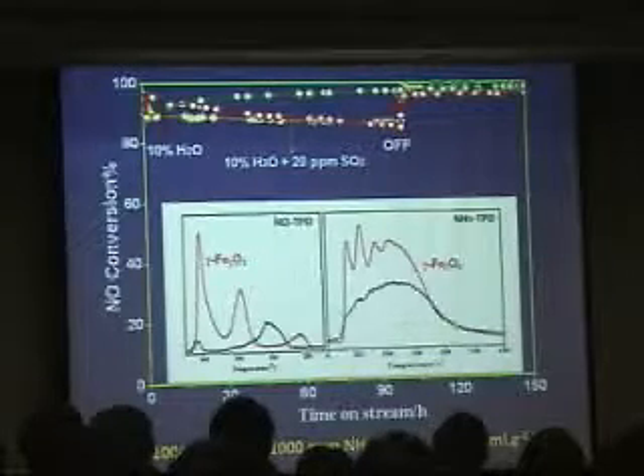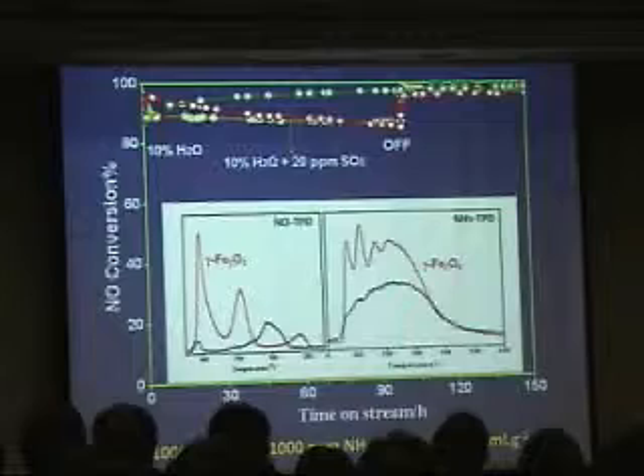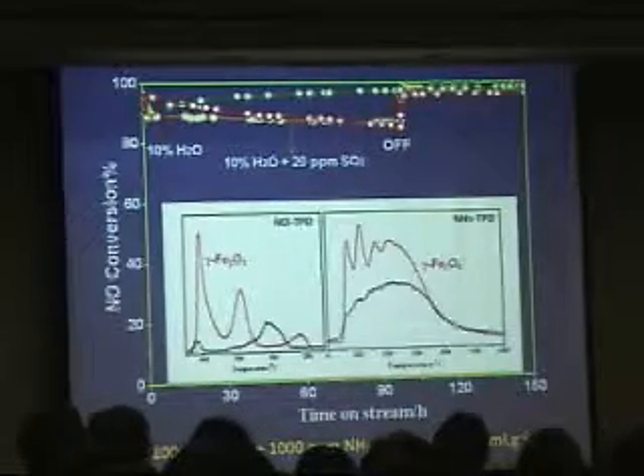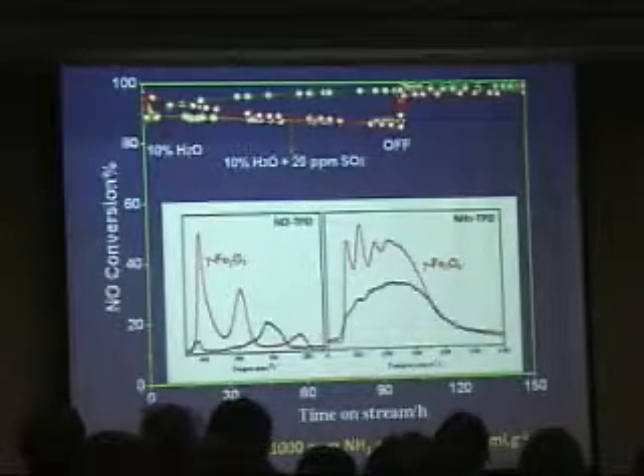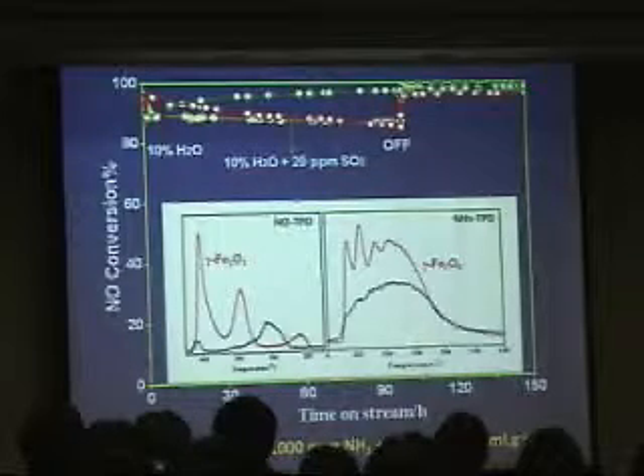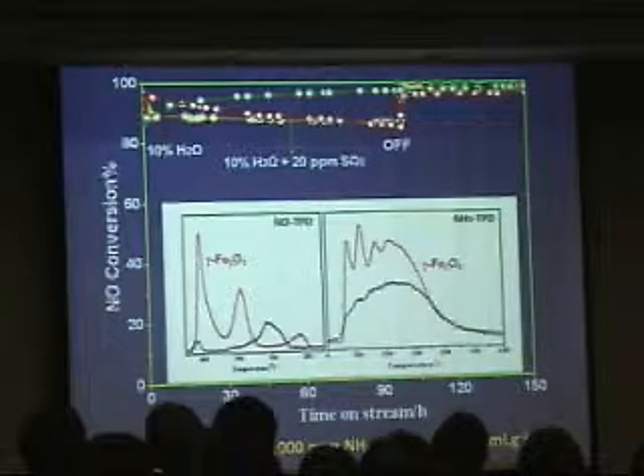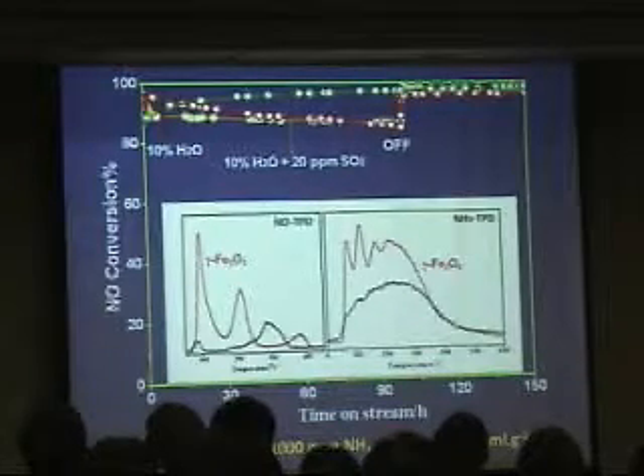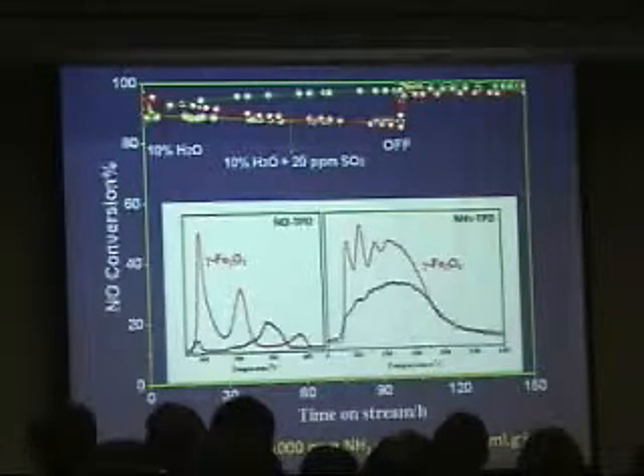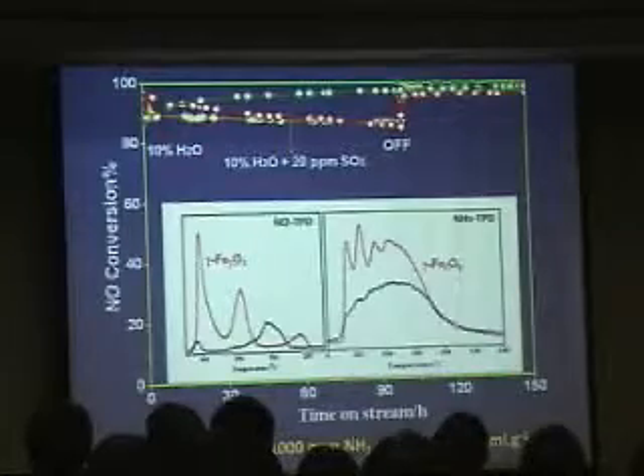After this, we examined many other oxides, and also found some similar phenomena of this kind of morphology-dependent catalysis. But there is a precondition that the diameter of the nanorod cannot be too large. If it's more than 100 nanometers or 200 nanometers, this kind of morphology-dependent phenomenon becomes not so significant. If it's less than 10 nanometers or 5 nanometers, it's more significant in changing the catalytic performance.